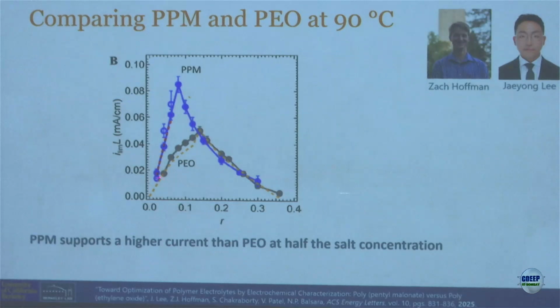So the first point is that the limiting current goes up, and then because of frictional effect, it goes down. And if you look at PPM, it goes up and down, but the peak is about a factor of 2 larger than PEO. So I claim that the best polymer electrolyte in the world is PPM, this polymer that somehow I was involved with in some capacity.